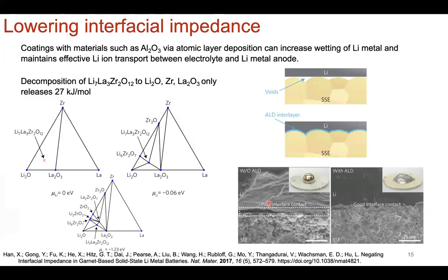So there are also other ways of bringing down the activation energy, and also making sure that the ion conductivity pathway actually migrates from the solid electrolyte to the lithium metal. And so this is what I was talking about before when it comes to understanding wettability of lithium onto these oxide structures.